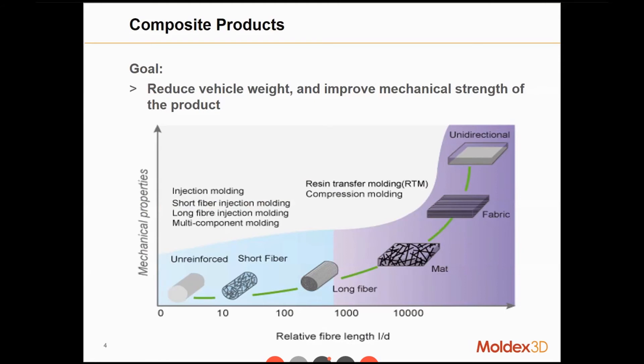But when both of those are not enough, we may go for fiber mat. Fiber mat may be something like SMC — the Sheet Molding Compound — or GMT, the Glass Mat Thermoplastic, which are often used for larger parts that require stronger structural strength, such as the oil pan in a car. We may use compression molding, the SMC process, to manufacture this kind of product. But when we are pursuing a stronger material and also lighter weight, we may go for fabric — or you can say it is a continuous fiber, or sometimes it can be unidirectional fiber, with unidirectional orientation.